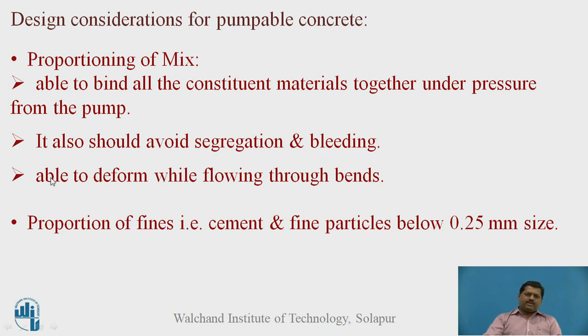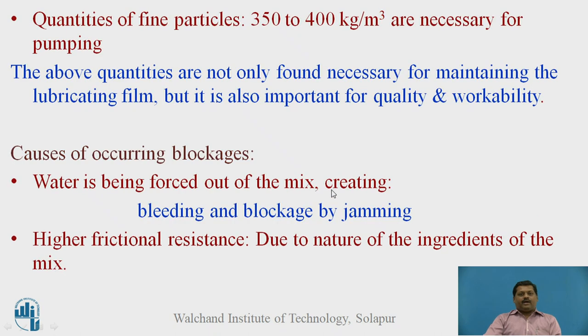Now, the proportioning of the mix must allow it to deform while flowing through the bends. Generally, for a short length there will be horizontal pumping, then the concrete will be lifted vertically. So, a bend will definitely be there. The concrete must deform in such a way, and proportioning is expected for that. The proportion of fines, that is cement and fine particles below 0.25 mm size, is very important.